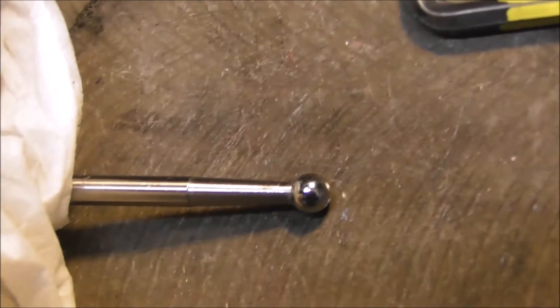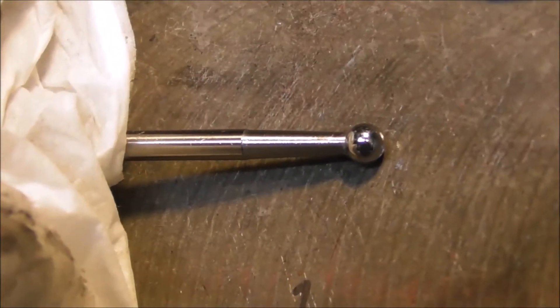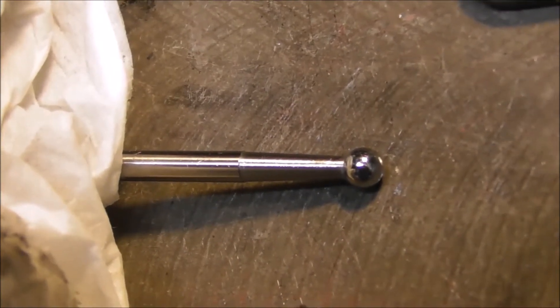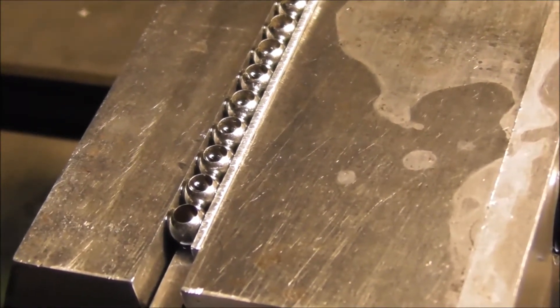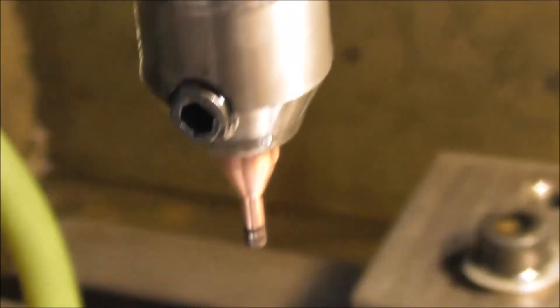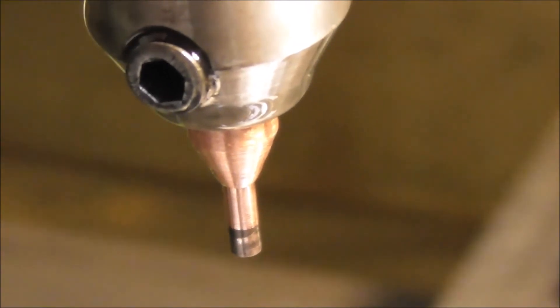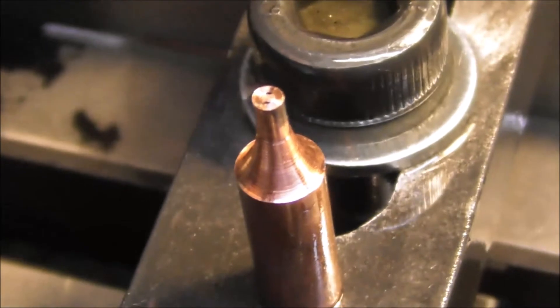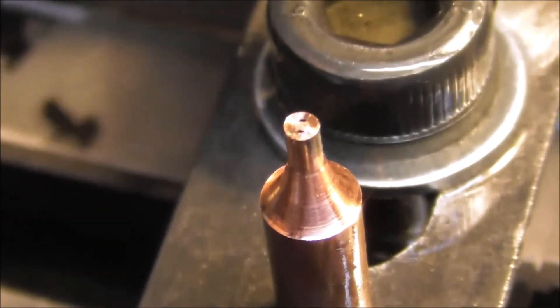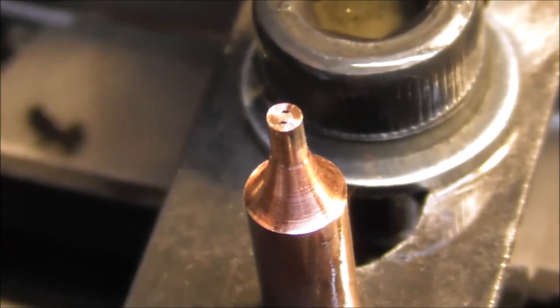The stylus stem is a piece of high-grade alloy steel, heat-treated alloy steel, cylindrically ground down to that 2.2 diameter and it fits into these little balls and is loctited in with a high grade of loctite and it just can't get it off once they are assembled. So this is spark eroded with an electrode, first of all with a roughing electrode and then with a finishing electrode. And it's quite a process, it's all about flushing. Spark eroding, here's a finishing electrode here. I don't know if you can see it there but there's two tiny little holes in the end there.